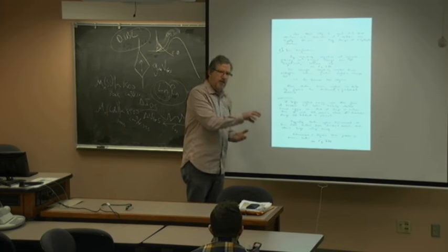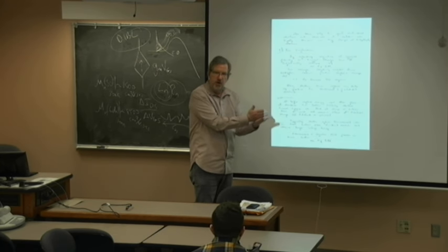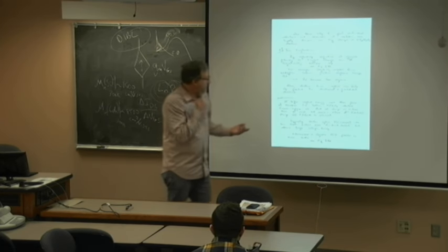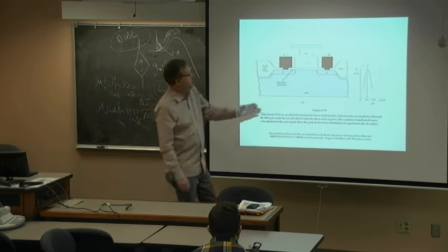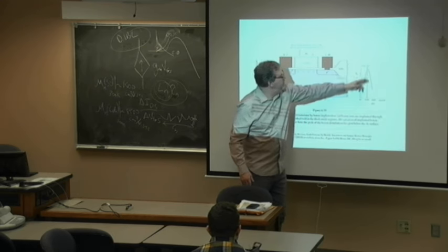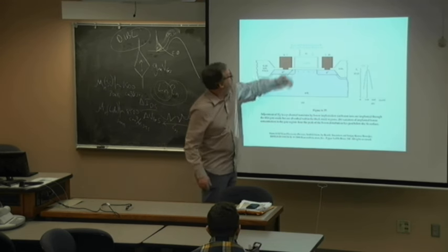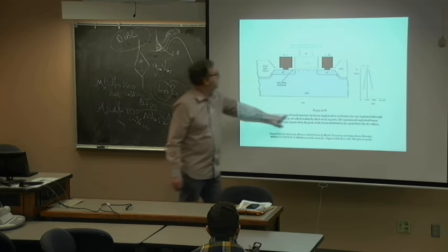But I can do ion implantation. That's very selective. So I can actually protect 75% of the transistors with photoresist, and I can do an implantation to 25% of the transistors and deliver a charge to adjust the threshold voltage. So I can manipulate a portion of the population of transistors and get that menagerie that a circuit designer wants. And I can tailor that very well. We saw that in the ion implantation, where I'm tailoring and delivering a dose. I'm delivering it precisely at the interface, and so I can do that and adjust the threshold voltage. So this one's adjusting threshold voltage in this particular manifestation.